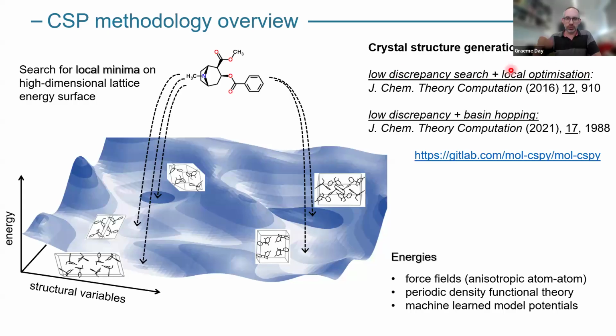And then we couple this just with simple local optimization. So we scatter a lot of structures across this energy surface and locally energy minimize them. And this is where most of the cost of crystal structure prediction comes in, doing this process many, many times. We have more sophisticated approaches where, rather than just a simple local optimization, we might do something like basin hopping, which is a trajectory from that initial starting point, which was generated from a low discrepancy sequence. That trajectory might be able to hop over low energy barriers, so we don't get trapped in very shallow local minima with this kind of approach.